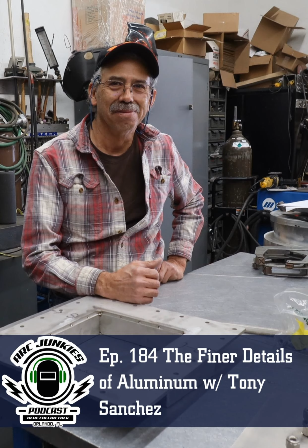Yeah, the only problem I've ever had on sub arcs is at one point on some startups, you'd get some pinholes. And what we ended up doing is building a couple purge dams and bled some argon right over the top of it, right in that area. Never had it anymore. It was just dragging oxygen. You get that heat in there and it's looking for that oxygen, and you end up with a few pinholes, just enough to get the grinder out. So I'm always trying to fix it before I do it. Right. So spill that argon on the backside of it. God, Tony, how'd you get that where you don't get pinholes? I don't know. Lucky, I guess.